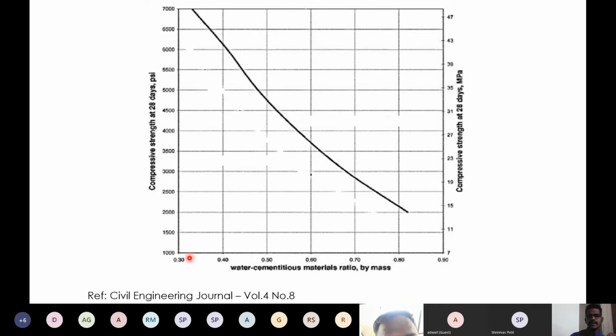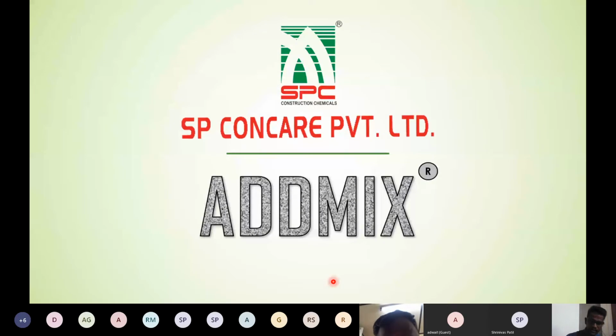As you can see here, at 0.32 this value is higher, around 50 MPa, and as the water cement ratio goes on increasing, the compressive strength starts reducing. So here you can see, the more the water cement ratio, the lesser the strength. The more porosity, the lesser the strength. For that, SP Concare Private Limited has designed the admixture under the brand name of Admix.